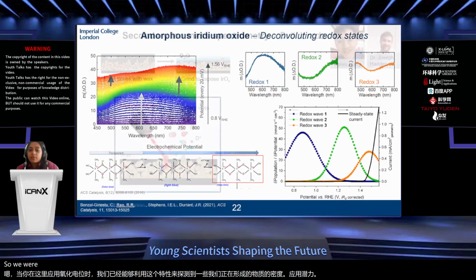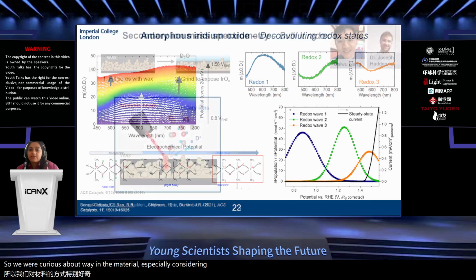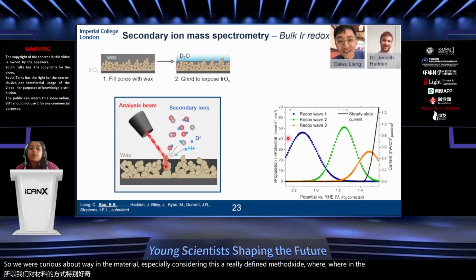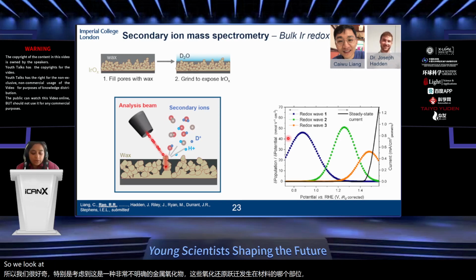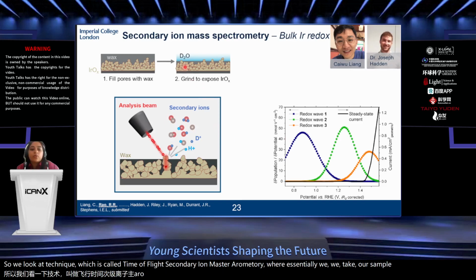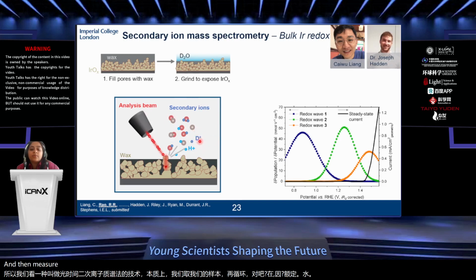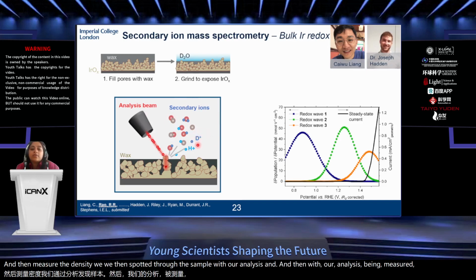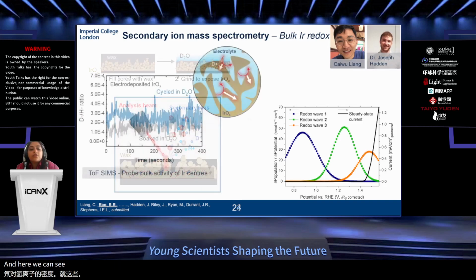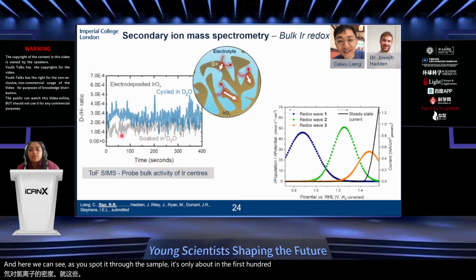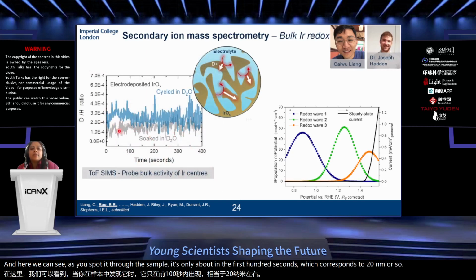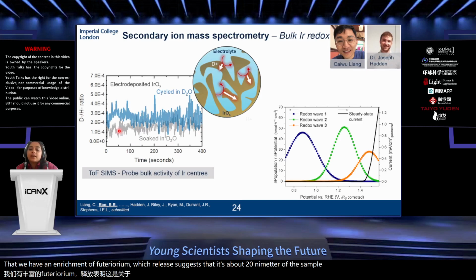So we were curious about where in the material, especially considering this is a really ill-defined metal oxide, do these redox transitions occur? So we look at a technique called time-of-flight secondary ion mass spectrometry, where essentially we take our sample, we cycle it in deuterated water, and then measure the density. We then sputter through the sample with our analysis beam and measure the density of deuterium to hydrogen ions that were evolved. And here we can see, as you sputter through the sample, it's only about in the first 100 seconds, which corresponds to 20 nanometers or so, that we have an enrichment of deuterium, which really suggests that it's about 20 nanometers of the sample that's catalytically active in this case.